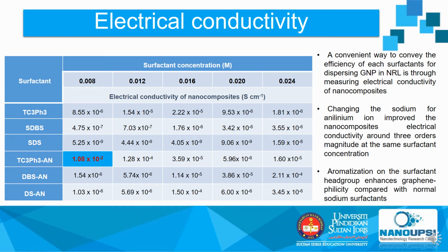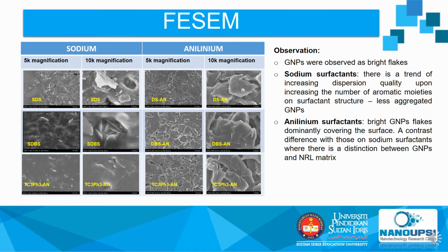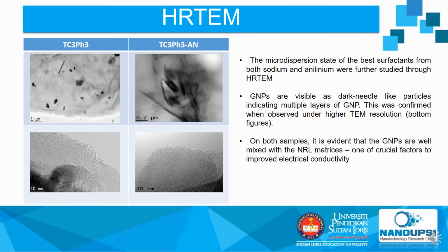So the first result is the four-point probe result, which is the electrical conductivity. As you can see, the introduction or increasing number of phenyl groups, not only on the surfactant chain, improves significantly the conductivity of the composite, up to 10^-2, and this is our FESEM image.